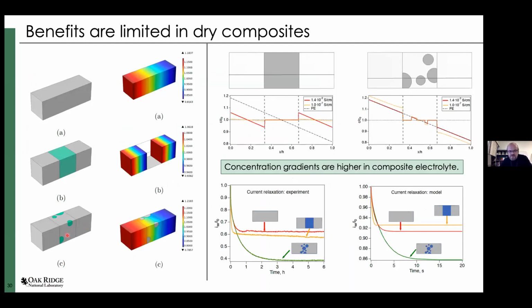If you place the composite electrolyte in the middle here, because you still need to observe the electroneutrality in the whole system, right? You develop much higher concentration gradients and obviously much higher polarization at the end. Unless you place a barrier in the middle which is not penetrable for anions in the polymer. In that case, you split this domain into two subdomains, and in each subdomain you have to observe electroneutrality, and the overall concentration gradient obviously diminishes. But using composite electrolytes with the dry polymer doesn't seem to be that feasible. And this has been confirmed experimentally as well. You can compare the simulation results with the experiments.